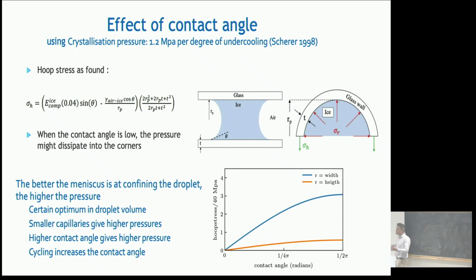All right. And so the only thing that is left for us is to try and understand the mechanics of this. And so we did a very simple calculation for simplicity in a cylindrical capillary, where we calculate the stress that the growing ice exerts on the walls. You'll have to believe me that this is the correct answer. The evident conclusion is that if there's a contact angle between the ice or the water and the wall, and the ice starts to form, if the contact angle is very high, there will be more pressure on the walls than when the contact angle is very low, because then the pressure will simply be advected to the sides.